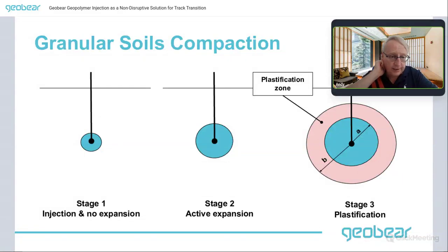So we have a process here where there's an initial injection into a granular soil, and there's no expansion. This is the cream time. And then during the gel time, there's expansion of the geopolymer within the granular material, and it starts to expand. And that expansion causes what we call a plastification zone, which is really a zone of densification around the expanding geopolymer bulb. So on completion of injection, you have a hard bulb of geopolymer, and surrounding that bulb, there's a zone of plastification or densification. This is where the soil has been physically moved out of the way.